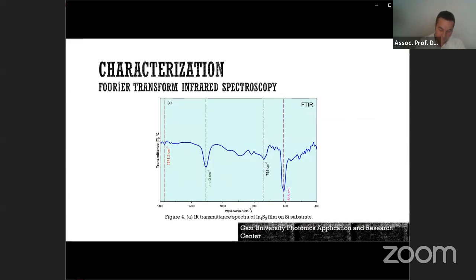Fourier transform infrared spectroscopy, FTIR. Also, you can see Figure 4. The absorption peaks centered at 1371 and 798 were attributed to indium-sulfur vibration modes of indium sulfide. In addition, two absorption peaks at 1110 and 610.5 originating from the silicon substrate were also observed in this spectrum. These results are compatible with previous studies.